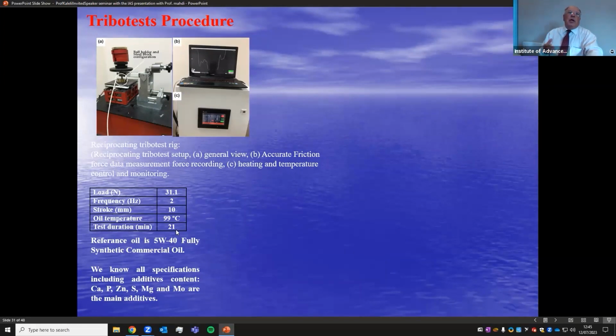Because I speak French, I have been in France, Lyon, at INSA many years ago, and I worked with Mr. Yves Berthier at INSA Institute. As I speak French, we collaborated together, and we tested these parameters on tribometer at INSA. Why these parameters? Because we like to obtain additive layers, just cover all the surface on the liner or on the sample we are carrying out. That's why I experiment for one lubrication condition, this procedure.